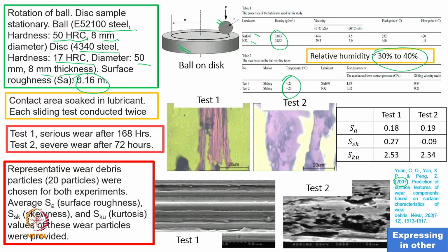You can see here the density difference is not that significant, however, the viscosity difference is significant. We can say SAE40 is a thick oil, and N32 in this case is a thin oil, and this viscosity is almost 3 times more at 100 degrees centigrade. However, N32 is much more stable; it will not deteriorate as much as SAE40 does with an increase in temperature. Flash point has also been mentioned, but of course we are operating at 20 degrees, so flash point does not make much sense for this purpose. However, for completeness it has been given, and even the pour point or flow point has been mentioned. Now, coming to the real experiments.